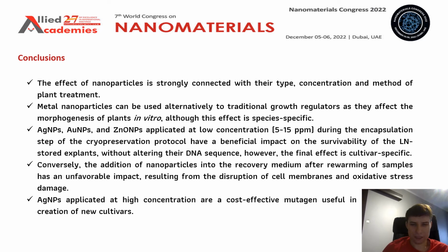Conversely, the addition of nanoparticles into the recovery medium after rewarming of samples has an unfavorable impact resulting from the disruption of cell membranes and oxidative stress damage. We know that because we have studied the activity of various enzymes in the plants after treatment with nanoparticles.